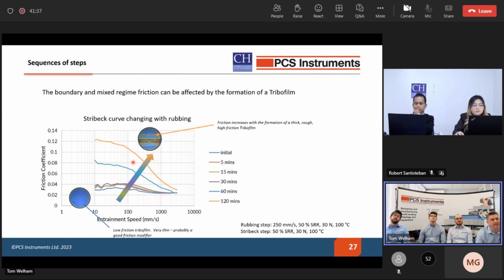And we do this repeatedly. So after 2 hours, we keep doing periods of time steps and then Stribeck measurements, and we can see how the tribo film has evolved, changing the level of friction in the contact as the test has progressed. And we can combine this with the MTM SLIM, which is the images here, which actually give us an indication of the thickness of that tribo film in the contact. And I think I'm going to pause here for some translation.